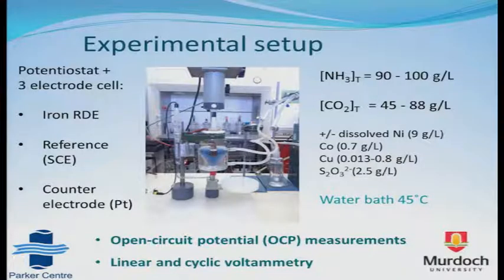To investigate this, I've used electrochemical techniques with a potentiostat connected to a 3-electrode cell, in which the working electrode for most of these studies was made of pure iron. There was a reference electrode to enable me to measure the potential of this iron electrode. And for those experiments in which I vary the applied potential, I used a platinum counter electrode as well.